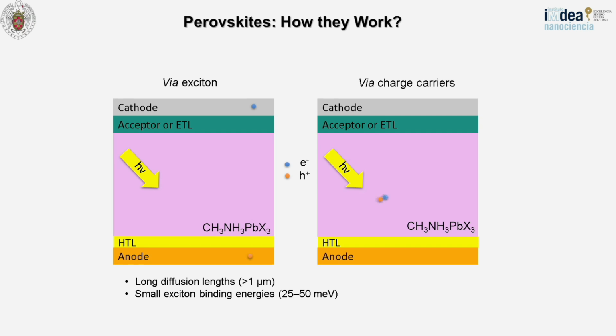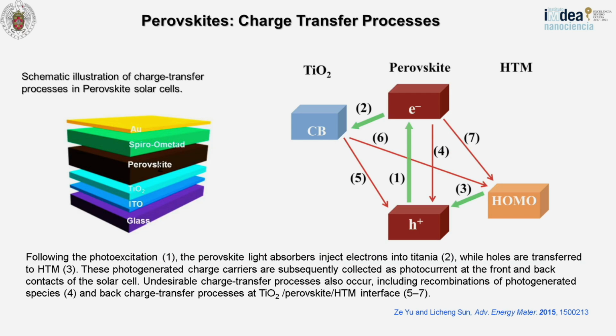Actually, for perovskite, like a good semiconductor, the charges dissociate within the photoactive material just to go to the electrodes. The reason is these values: very short binding energy and very long diffusion length. Okay, so when you excite the perovskite, these are the charge transfer processes occurring.